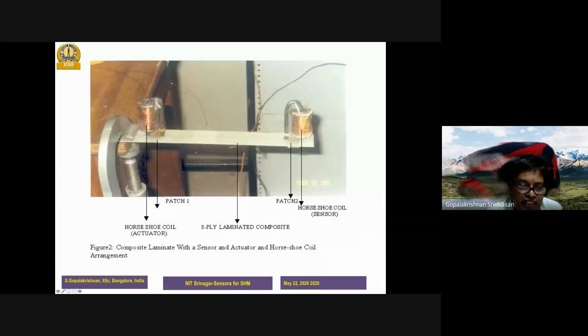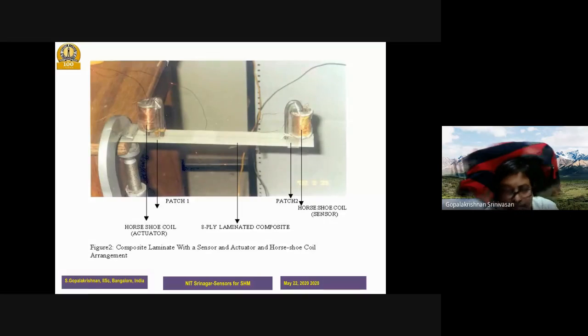And this is the schematic. So we used a horseshoe system with a number of coils to induce the magnetic field, which passes into it. This is used as an actuator coil. This is used as a sensor coil. So we excite this using current, and if the delamination is somewhere here, using the open circuit voltage between the sensor and actuator, I should be able to find out where the damage is.